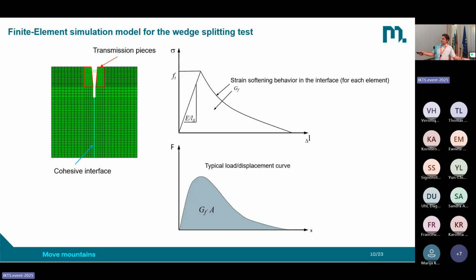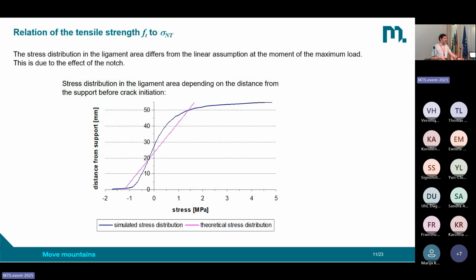Why? Because fracture starts at the top element and propagates through the sample, and the peak is reached in consecutive order. So the peak is first reached for the first element and then later for the lower elements. That's why we are getting this nice round shape of the load displacement curve. So, okay, we did our simulations.